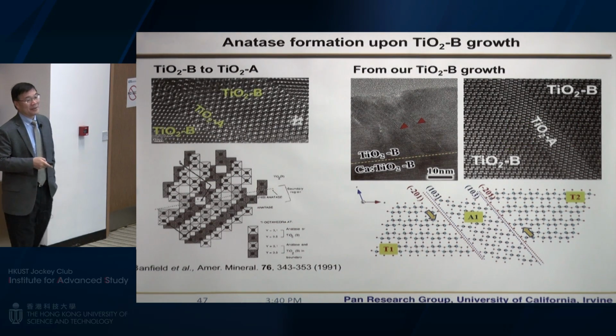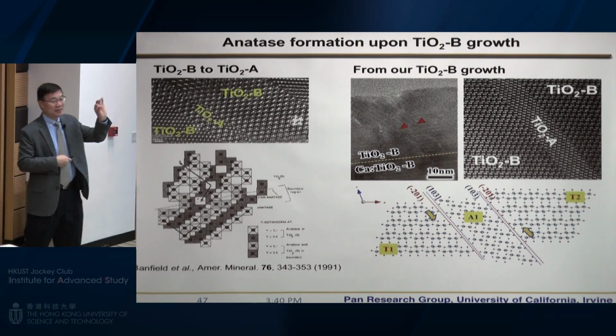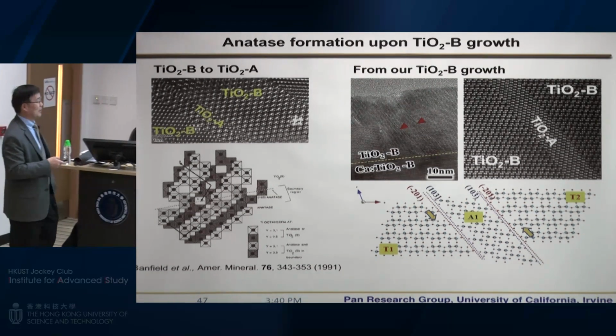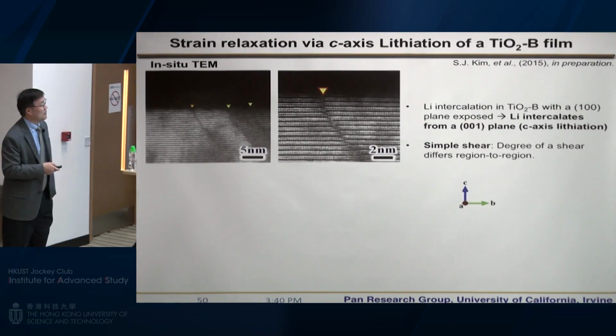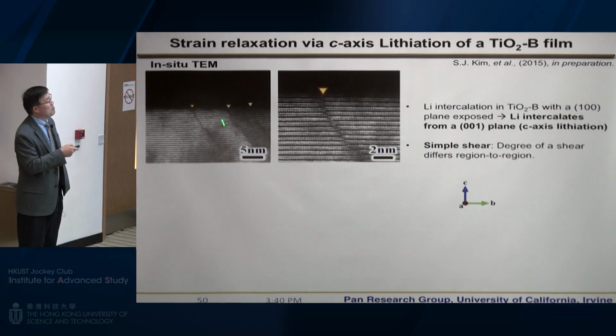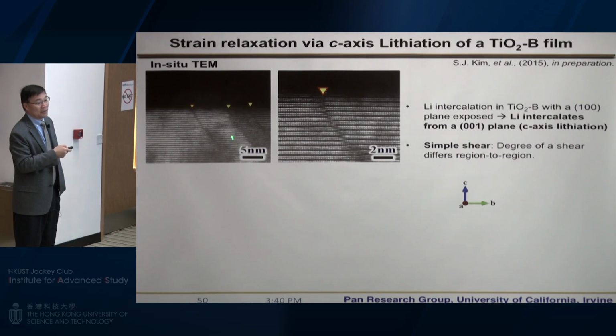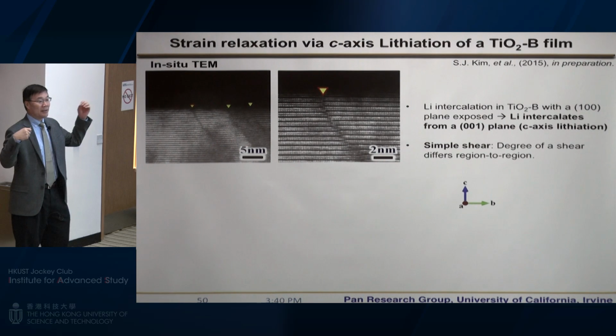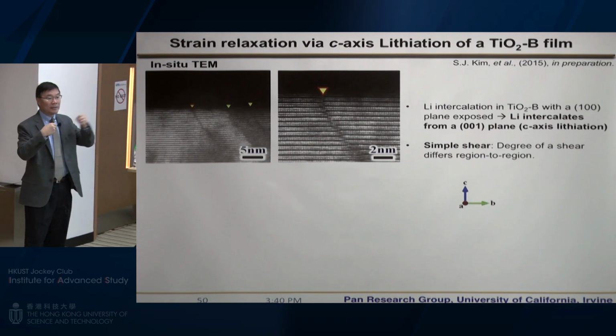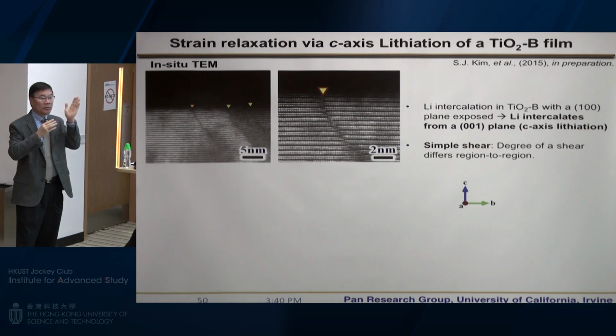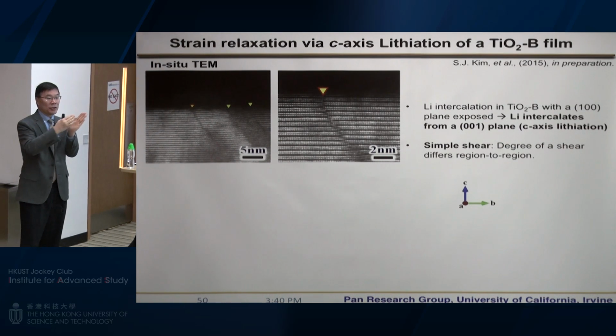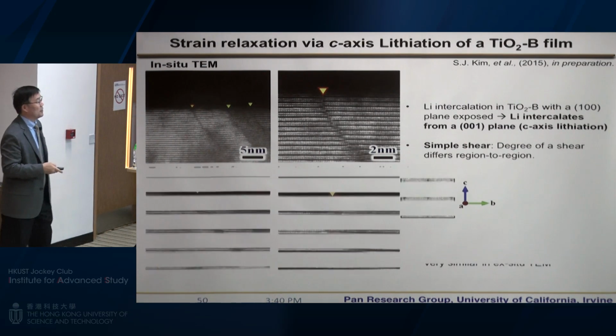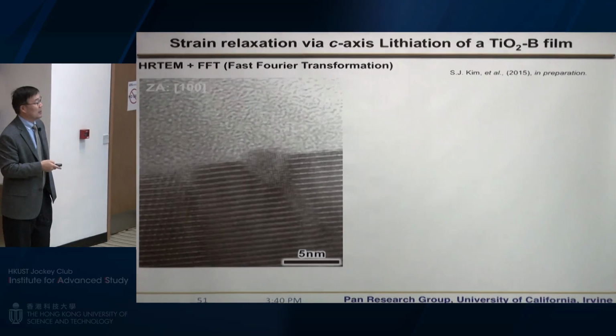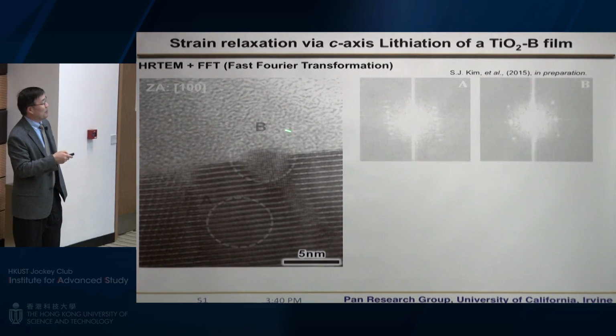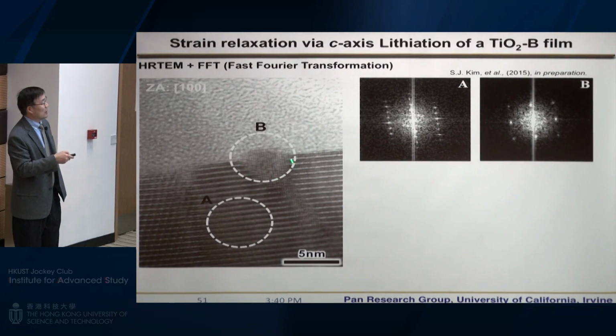And he tried and couldn't do it. It's just a limited amount of the planar defects, with anatase. But he will see more shear planes. We have a lithium insert, and then the volume is changing, and then the volume change generates strain. And the strain relaxation, one of the mechanisms is shear plane. Generate a lot of shear planes in the structure. Okay? So, and there's some area, even with the structure, which is completely different from the bronze structure.